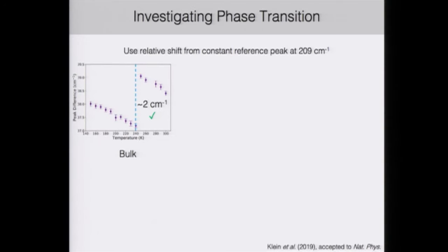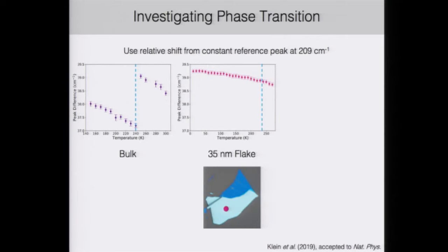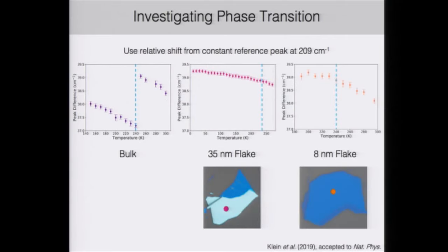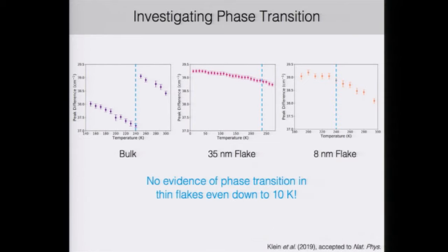So first, when we measure our bulk Raman spectrum, we see right at 240 Kelvin in the dashed line, we see a jump in the energy by about 2 wave numbers. However, when we looked at thinner exfoliated flakes, we saw that not only was there no transition at 240 Kelvin, but in this sample, we even measured down to 10 Kelvin, below the Néel temperature, and saw no evidence of this phase transition occurring. So this led us to ask, does this mean that thin chrome chloride is remaining in the monoclinic phase even down to low temperatures below its magnetic ordering?